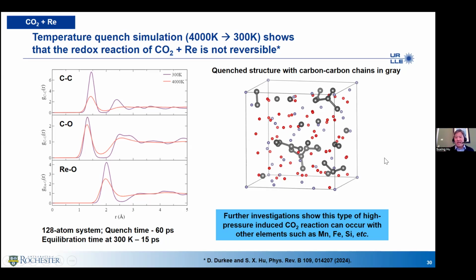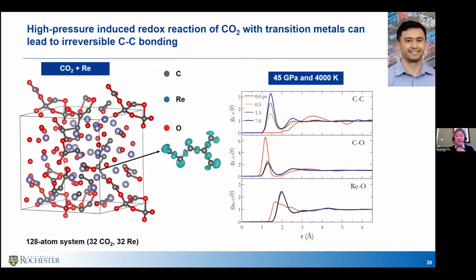The last bit is that this kind of behavior not only happens for rhenium, but other transition metals like manganese and iron, even silicon. If you put silicon in such a system, it will do the same trick. It will facilitate the decomposition of CO2. And again, back to the diamond formation possibility. If you look at his g(r) plot, it shows the CC bonding is very close to 1.5 angstrom, which is almost exactly the diamond CC bond distance.